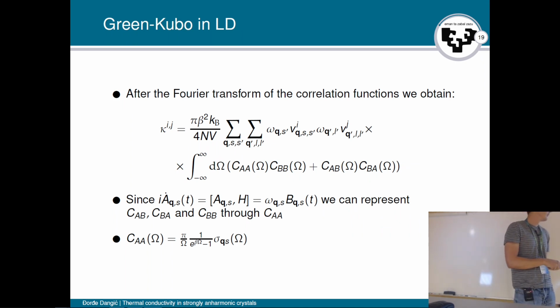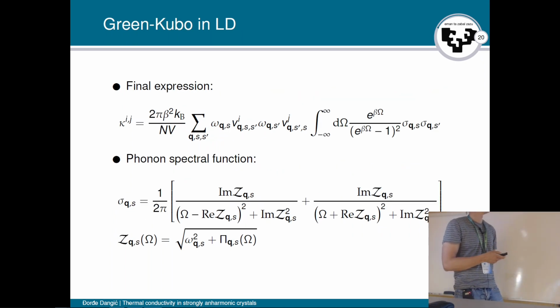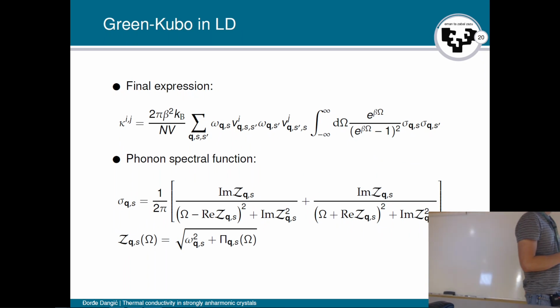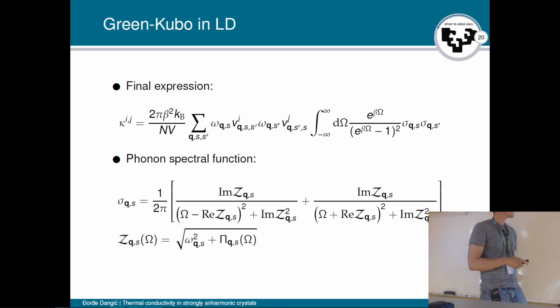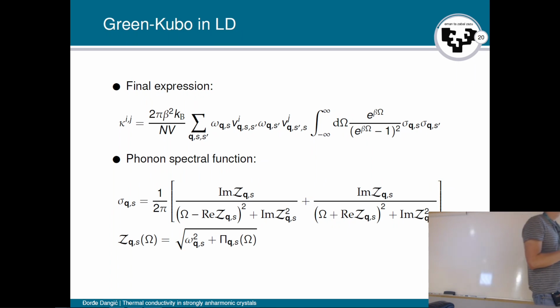Okay, so we substitute this expression for CAA into this equation, keeping in mind the various ways these other correlation functions depend on CAA, and we get the final definition of lattice thermal conductivity in the Green-Kubo approach. And as you can see here, we only have the sum over one phonon wave vector and two phonon branches. Again, we have the phonon frequencies and the phonon group velocities, and we have this integral, which is actually the main part here. And here we have the phonon spectral function.